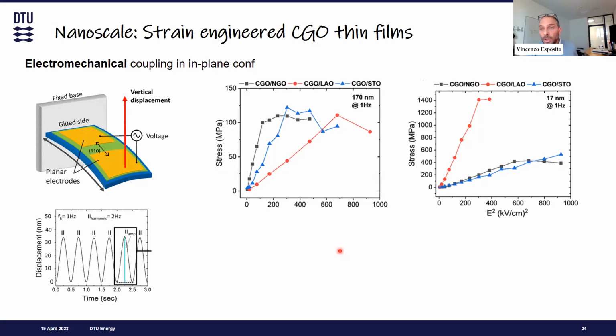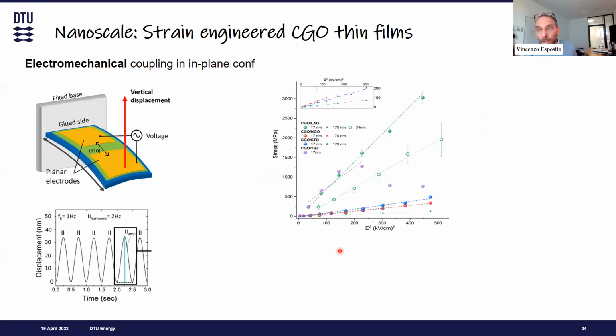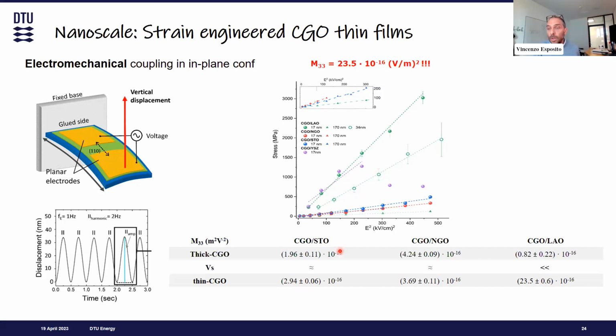And we have done these experiments a few times, and we have also included other substrates, and the compressive strain is confirmed to give a much higher electrostriction in this cantilever configuration. It is gaining at least one or two orders of magnitude with respect to the polycrystalline system. And this is extremely impressive. So the conclusion is that the in-plane compressive strain favors the electrostriction effect.